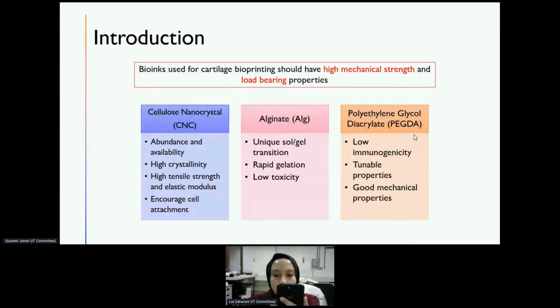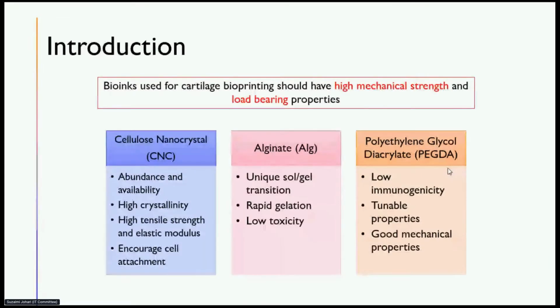And the third biomaterial is PEGDA. PEGDA has been approved by the FDA and has been shown to have little to no immunogenicity. Therefore, it is less likely to provoke an immune response, which is important in bioprinting applications. And the advantage of using PEGDA is that we are able to tune the properties, which means we can use different molecular weights of the PEGDA, also use different concentrations, and control the UV exposure to match the properties that we would like. PEGDA also has good mechanical properties that are suitable for the cartilage.